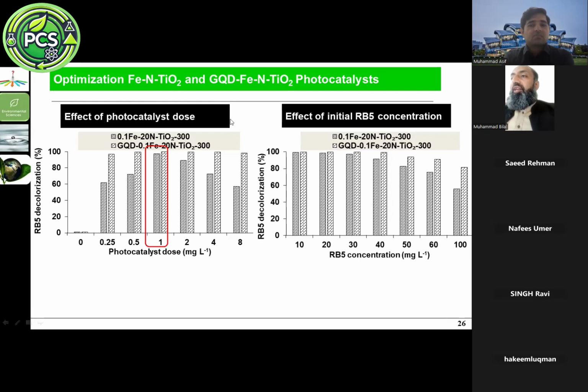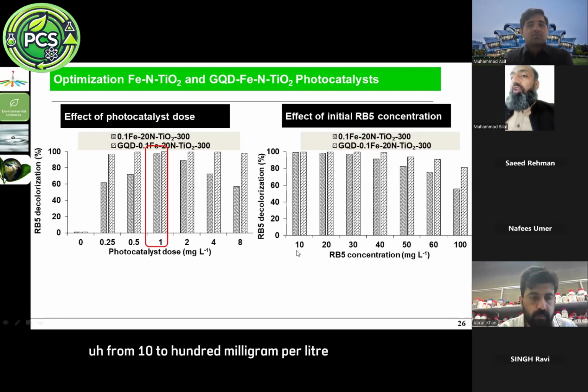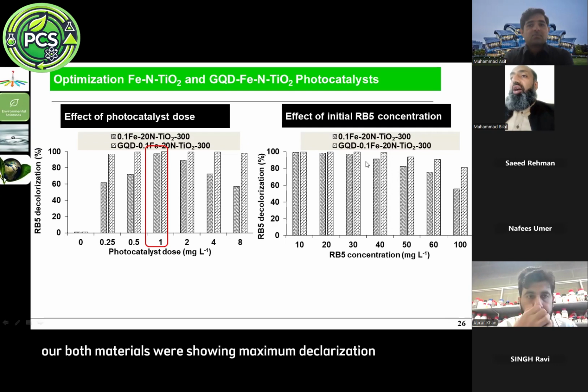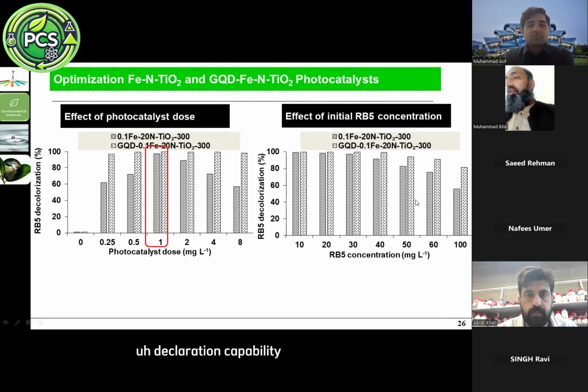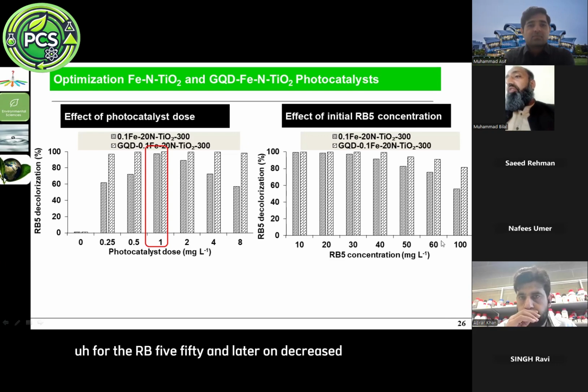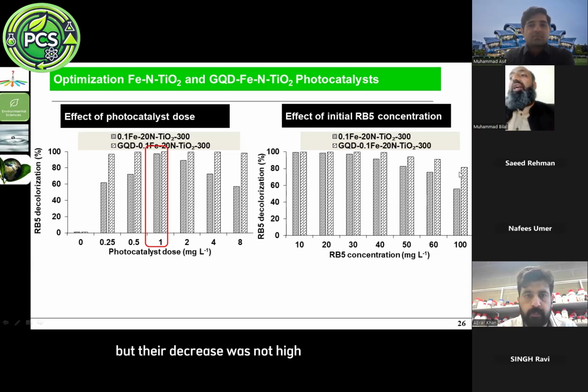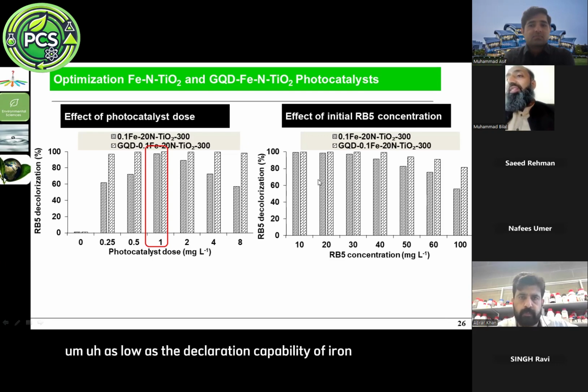So when we increased the concentration of the dye in the solution from 10 to 100 milligram per liter, both our materials showed maximum decolorization till almost 30. However, our finest material, graphene quantum dot iron nitrogen titania calcined at 300 degrees centigrade, showed excellent decolorization capability for RB5 till 50, and later it decreased, but the decrease was not as high as the decolorization capability of iron nitrogen titania. Still, almost 80% of the material showed degradation potential.